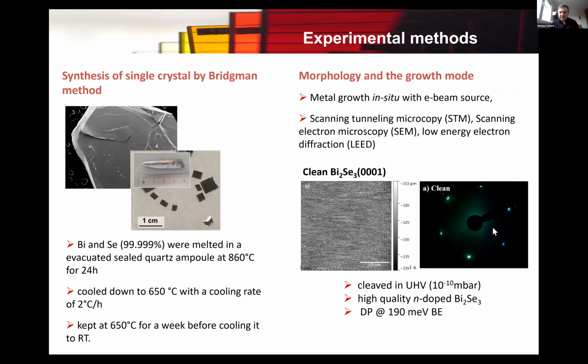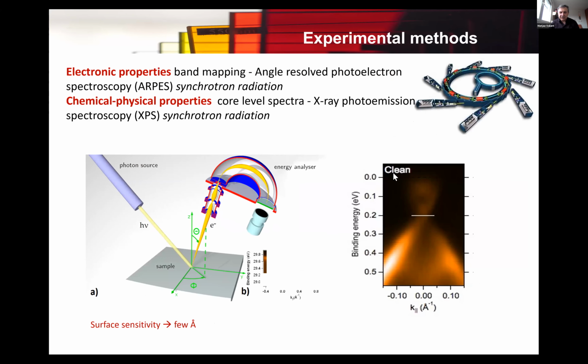Here we got the LEED pattern. We see it's a very nice rhombohedral pattern. The STM also shows a very regular surface structure. We have also done ARPES and see that the Dirac point here is at 190 milli electron volts. These are also synchrotron techniques that we are using to analyze the surface.